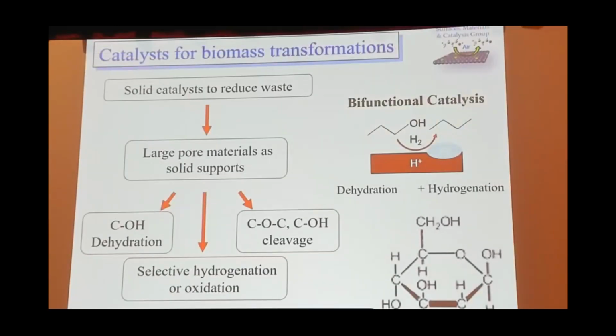So if you want to do a simple deoxygenation, say to make a hydrocarbon fuel, if you're working with an alcohol, your first step would be dehydration over an acid catalyst. Second step would be the hydrogenation step. If we can combine those two catalysts rather than working with two separate ones and having separation steps, it will make the process overall efficient. So looking at bifunctional catalysts for cascade reactions is really the direction that we're heading.